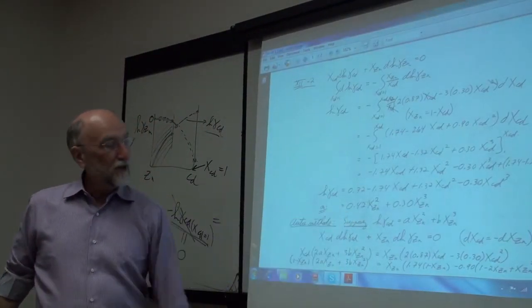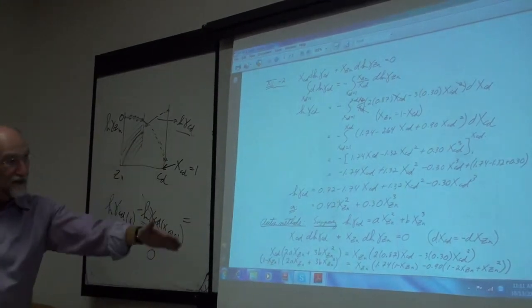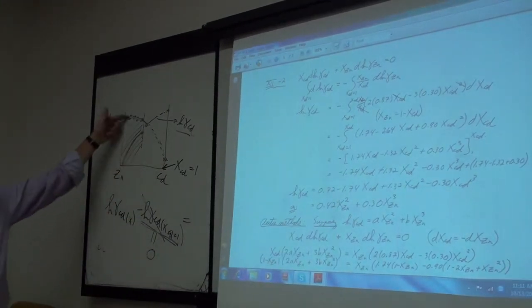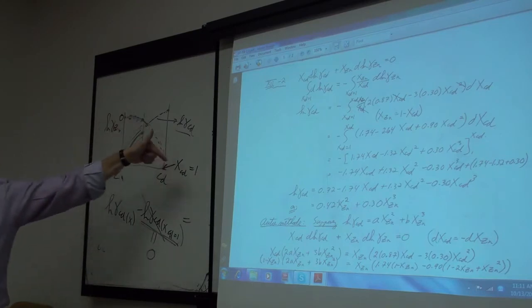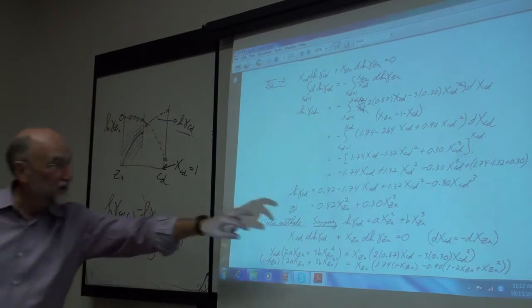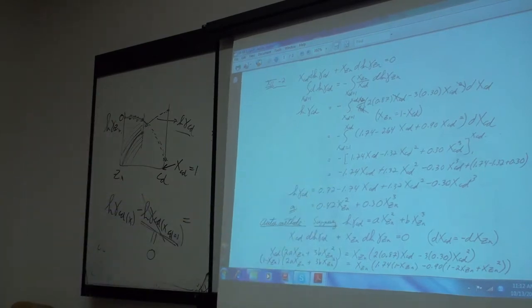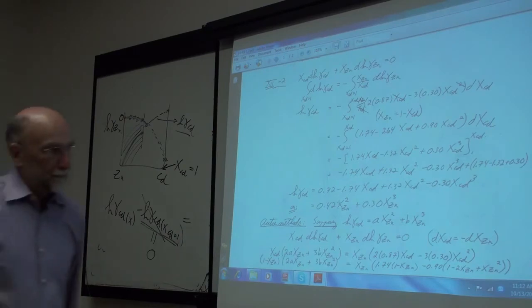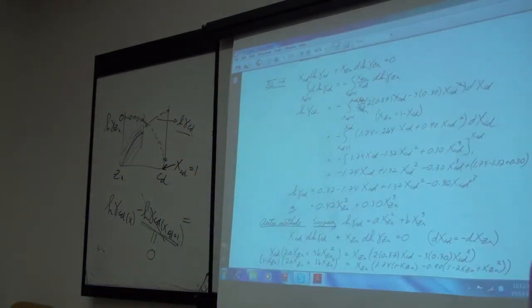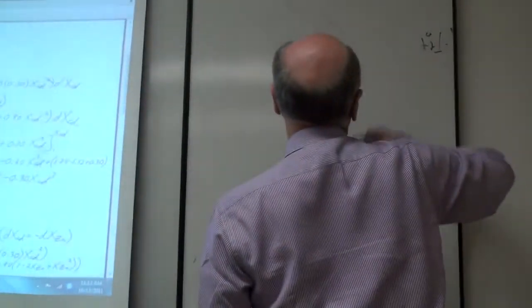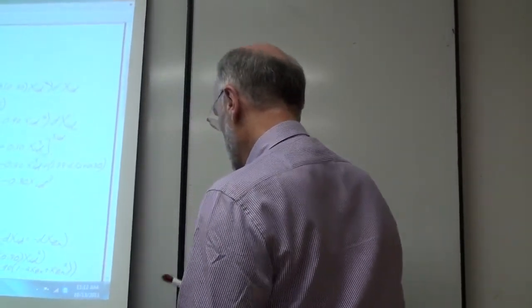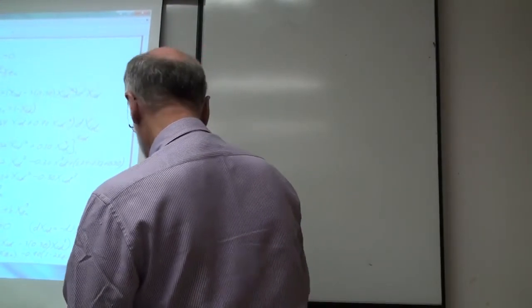Okay, and you say that just looks wonderful, but there's a hidden thing in there. The hidden assumption is that the equation for log gamma zinc applies over the entire composition region, and if it doesn't, then this doesn't apply over the whole composition region. But you can lose track of this, and you see this a great deal in the literature. In fact, you see it an awful lot. And this is what you generally see.